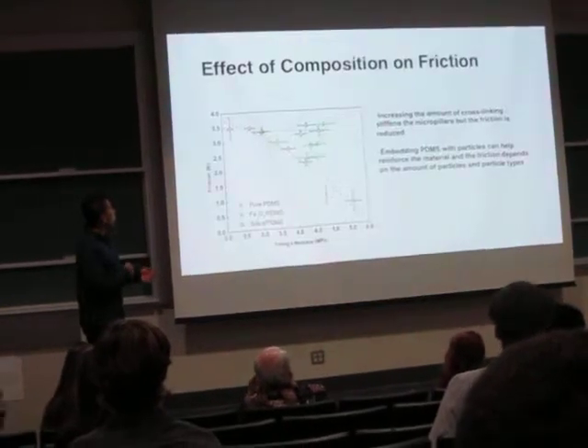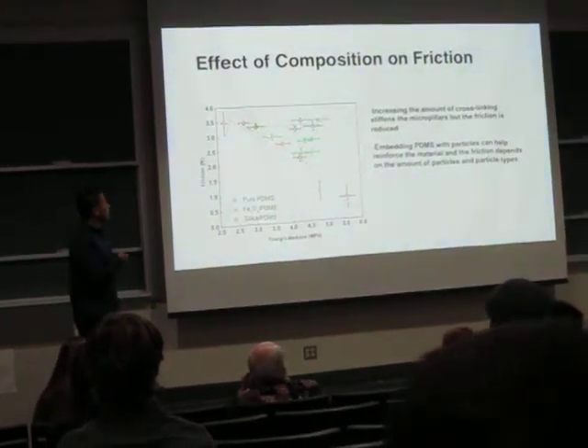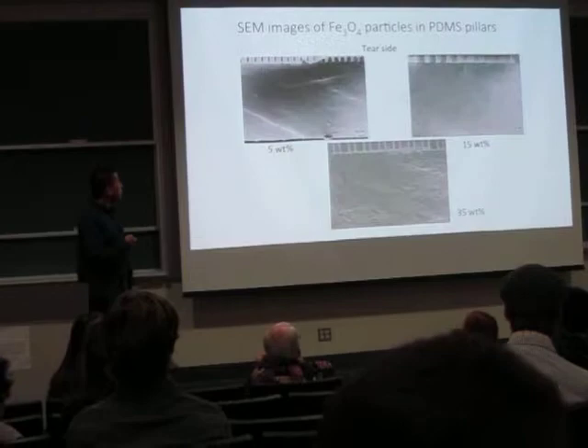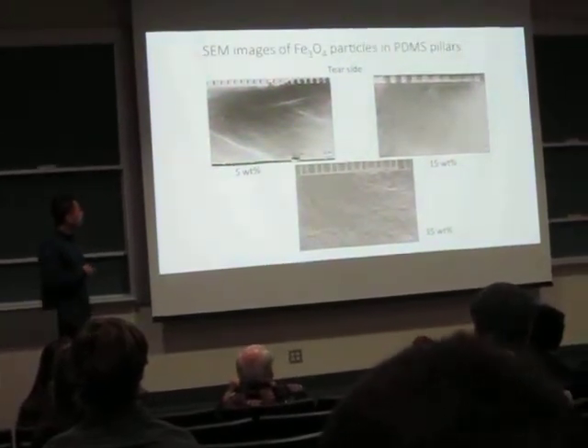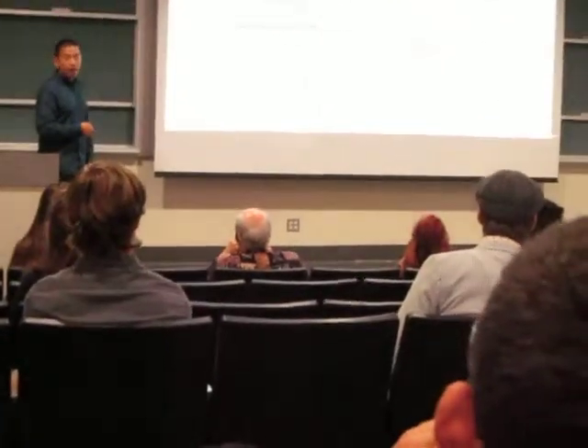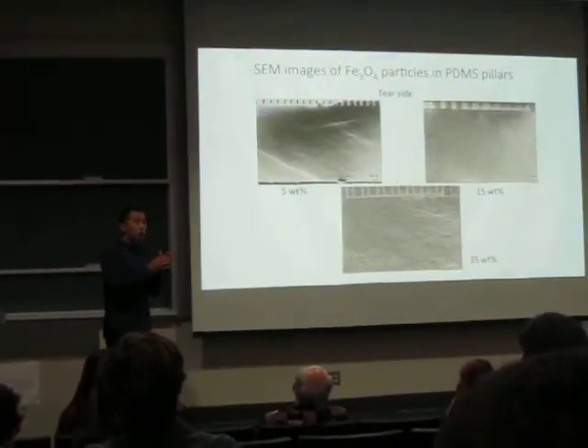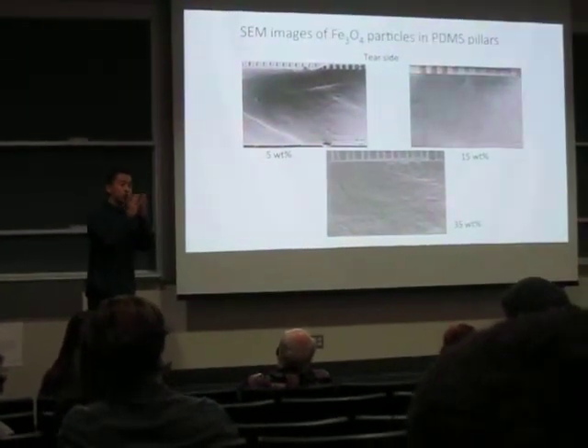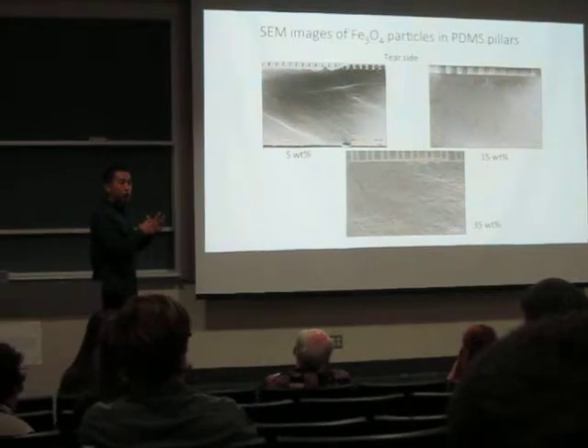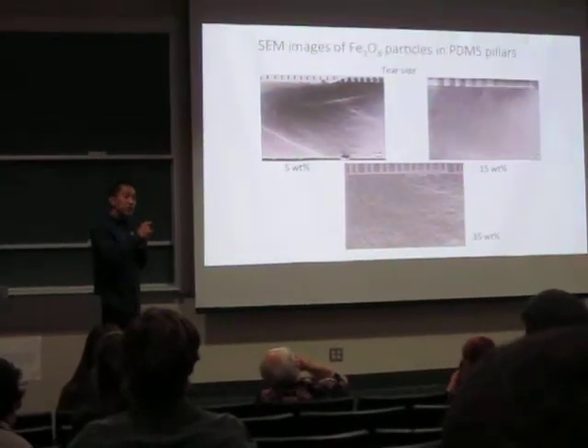So we did more investigation on why, when we're adding the black iron oxide, it drops first and then increases again. We took the SEM picture for 5 weight percent of black iron oxide, 15 weight percent, and 35 weight percent. For 5%, as you can see, all the particles disperse evenly. So we know the pillar is well dispersed, which makes sense because the pillar was pretty soft before. Now we're adding particles, which basically makes it harder, so it reduces the frictional force.